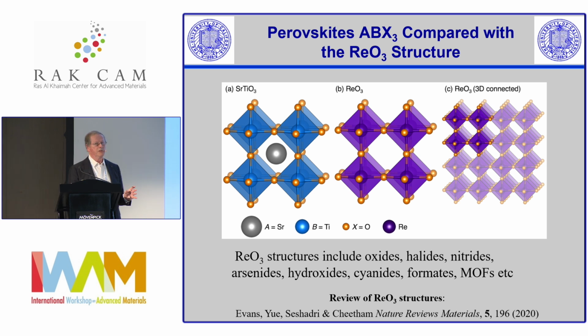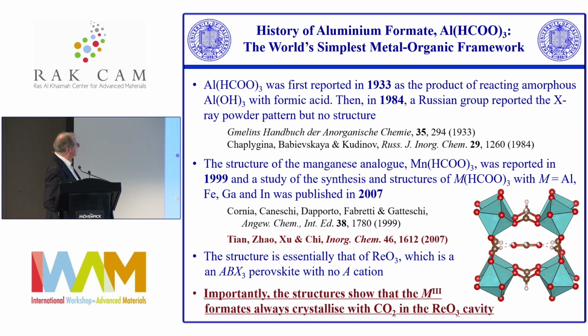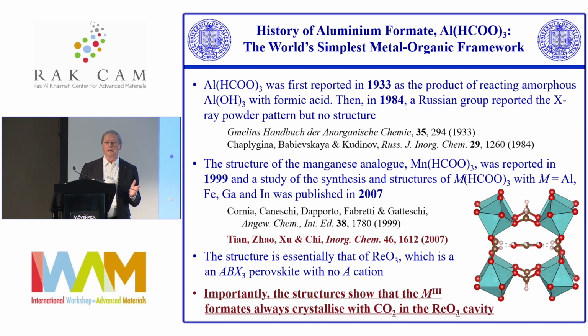But much to my surprise, you can make rhenium trioxides with a huge range of different linkers and so on, which had not been drawn together previously. And so one of the things that this did was focus our attention on the formates that we'd been working with for such a long time. And so aluminum formate is a very interesting compound, it turns out. And this is the first of these materials to have been made. It was first reported in 1933, so it's in the Gmelin Handbook of Inorganic Chemistry. And it was made from reacting aluminum hydroxide and formic acid.